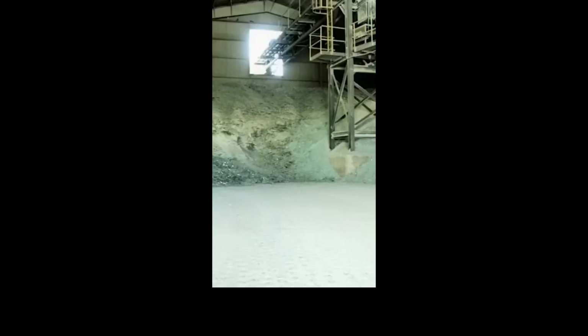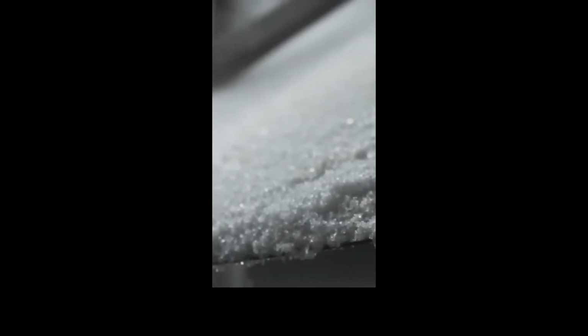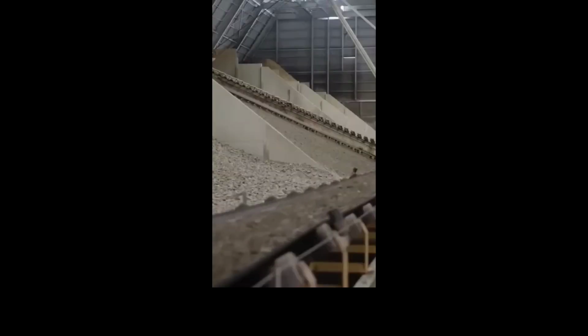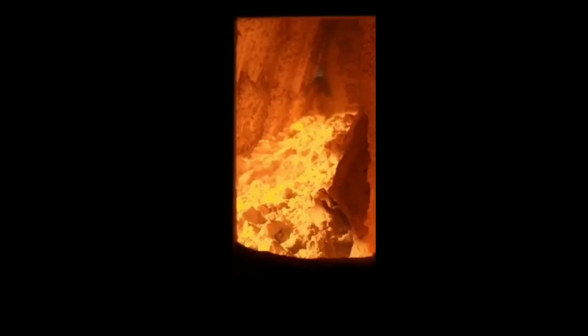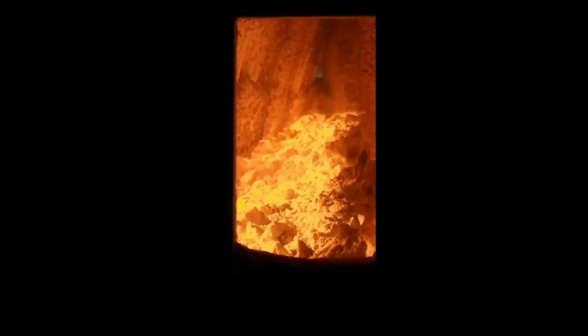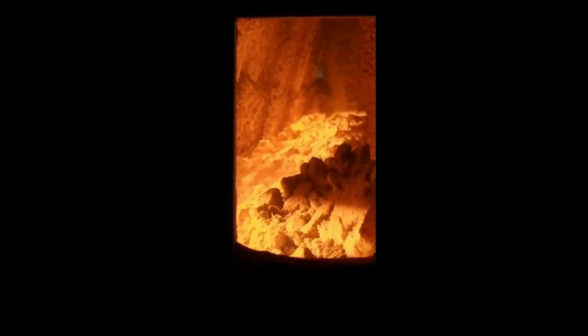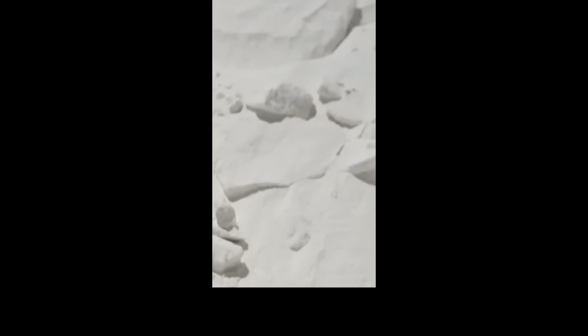Once the ingredients are ready, they're fed into a giant furnace. These industrial furnaces are built with refractory bricks and can run 24/7 for over a decade without shutting down. Inside, the mixture heats up to around 2,900 degrees Fahrenheit, 1,600 degrees Celsius, and turns into molten glass. This molten liquid flows into a hotter zone to eliminate bubbles and imperfections.